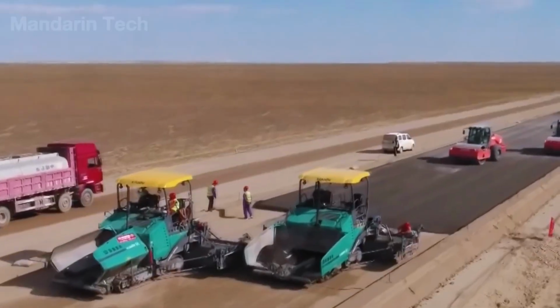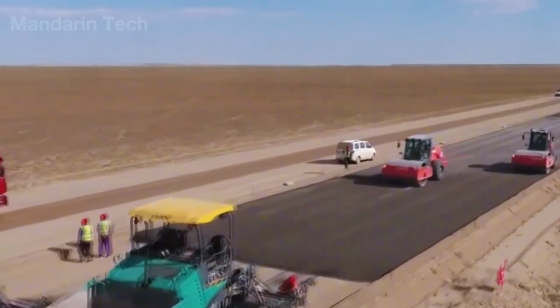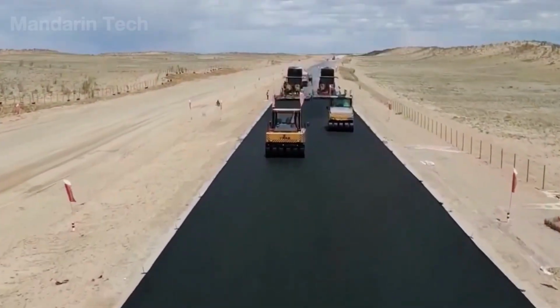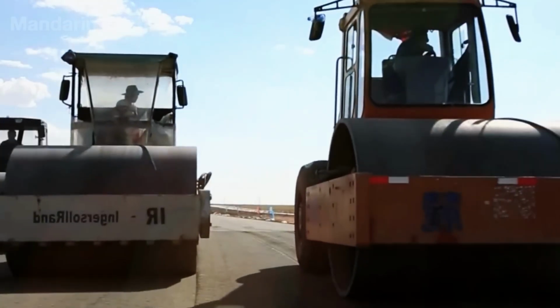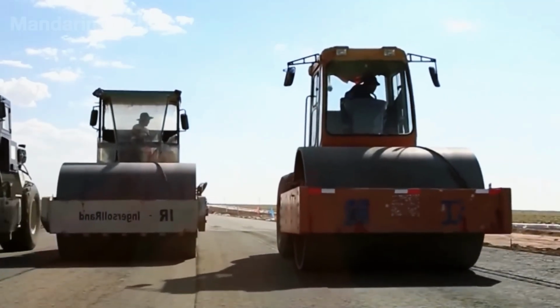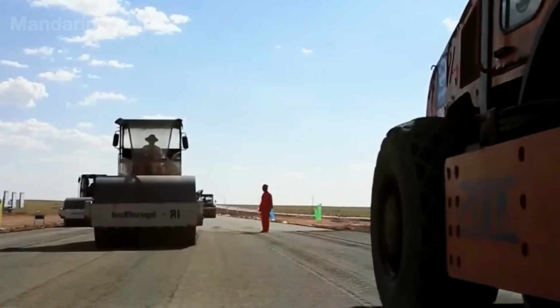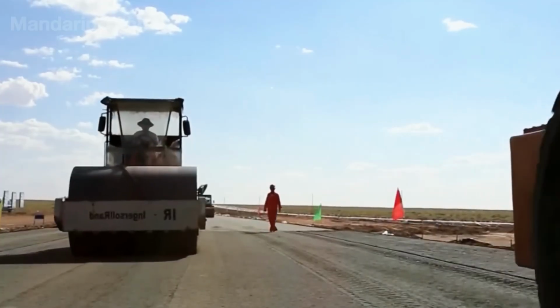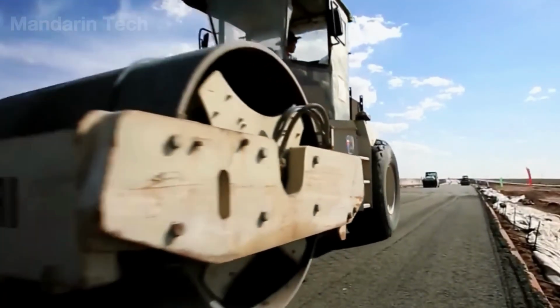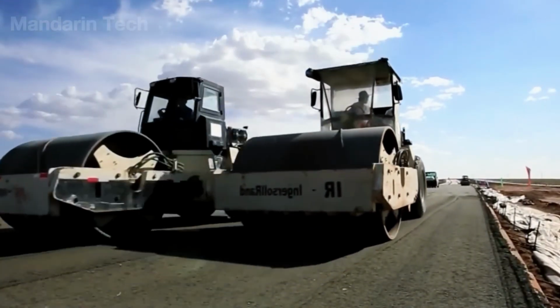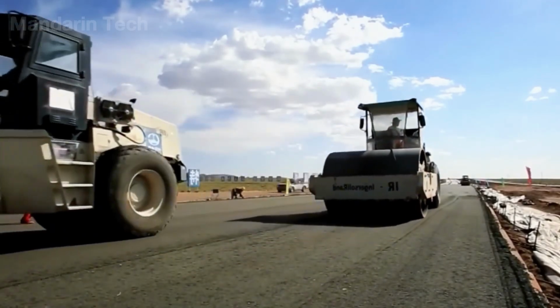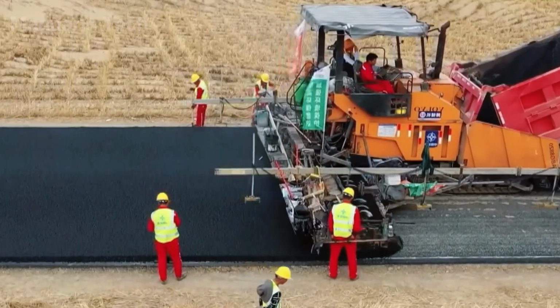The first passes used heavy steel drums for compression. The final ones switched to rubber tire rollers, which kneaded the surface to seal tiny air gaps and create a smoother texture. Thermal sensors on each paver tracked the surface temperature in real time. If the asphalt dropped below 140 degrees Celsius, rolling stopped immediately. Otherwise, cracks could form once it cooled.